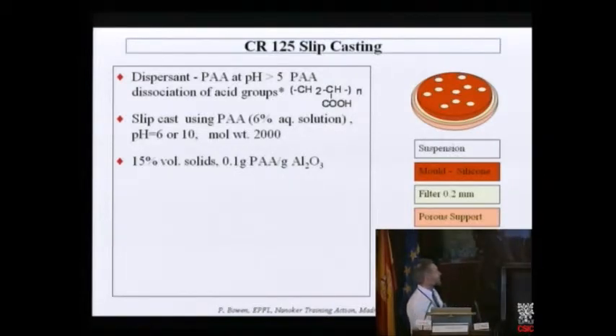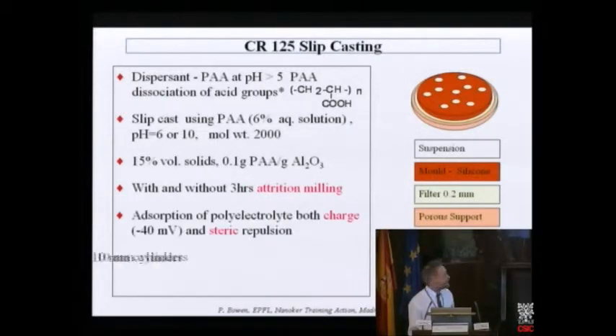You end up with only 15% volume solids. These are still aggregates. There's still an internal porosity in the aggregates. So this is relatively low. But as you saw on the last slide, if you've attrition milled, you can still get the 99% density with simple natural sintering. Basically, these adsorb. They give you this charge and steric repulsion, and you can make these nice cylinders.